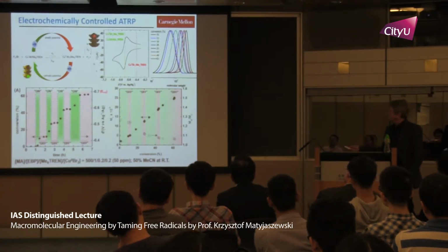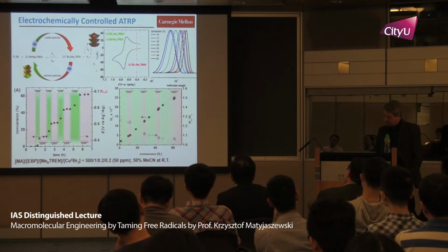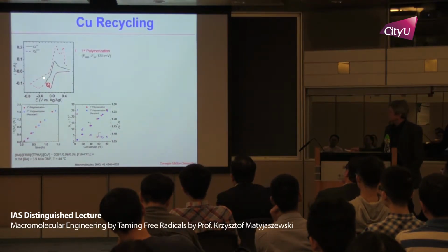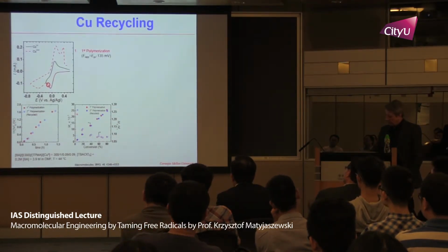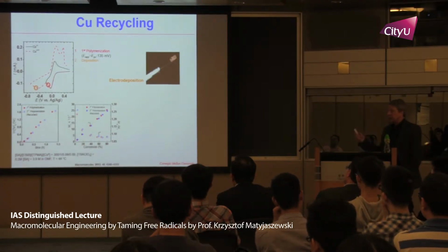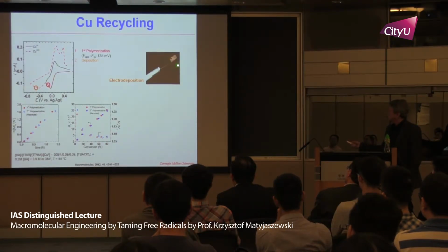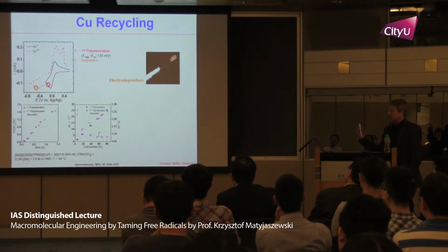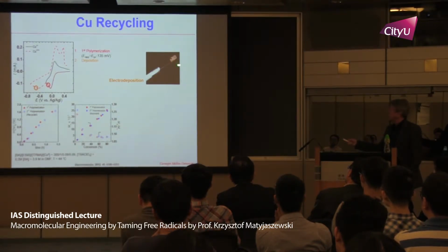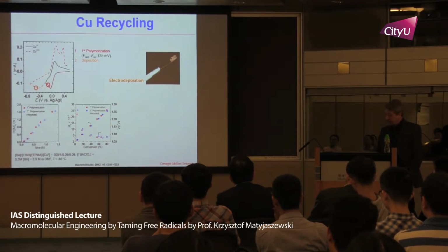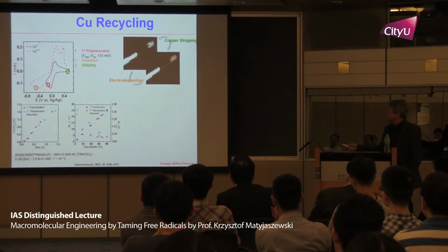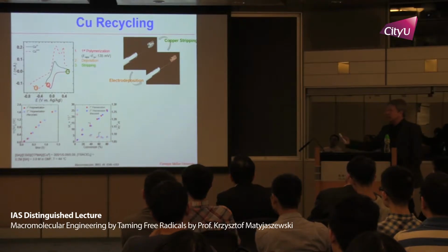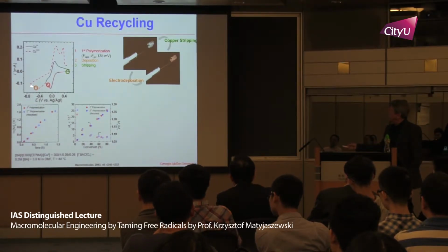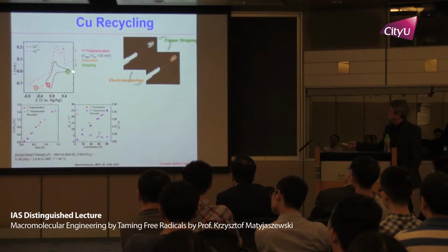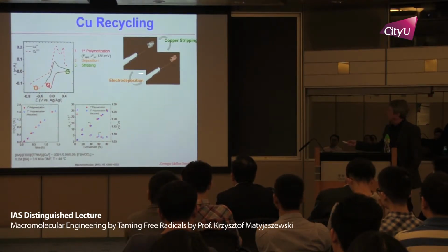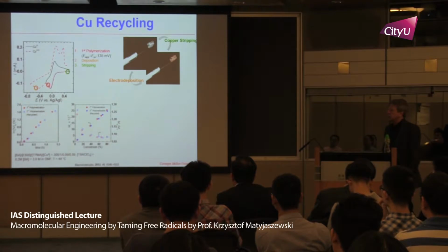However, you have to be careful. If I go to more and more negative potential, you start really seeing a second peak. And then, if you look at what really happened to the electrode, you start seeing that this platinum electrode gets shiny like a copper electrode, because copper gets deposited. So in that case, what happens, you really deposit copper on this electrode, and if I go to a more positive potential, I can strip this copper, and I get a shiny platinum electrode again.